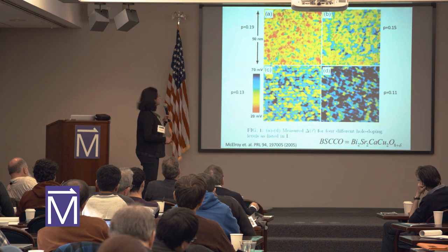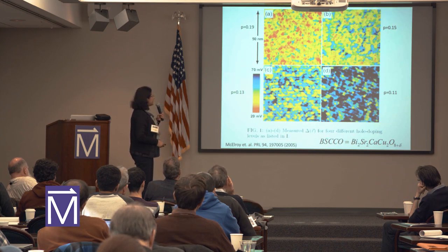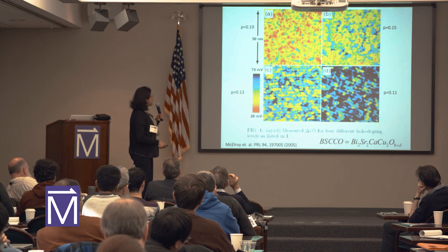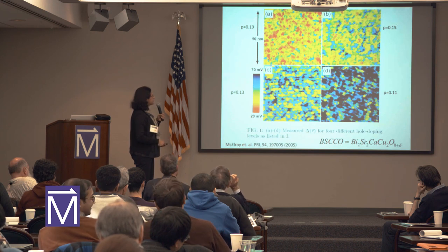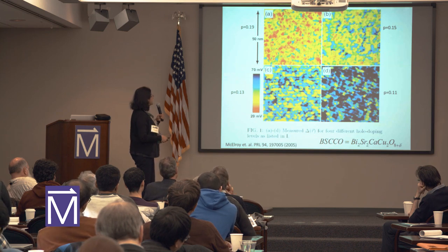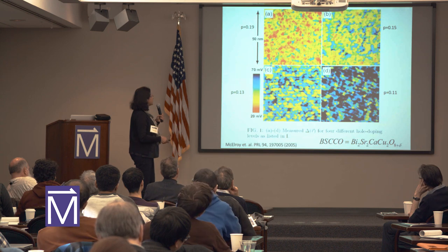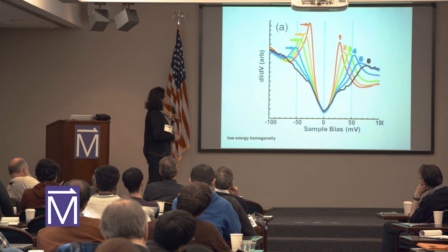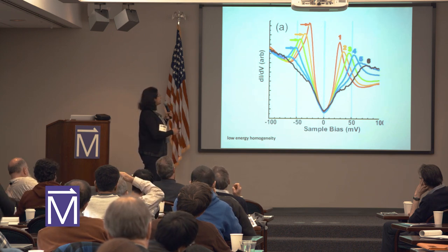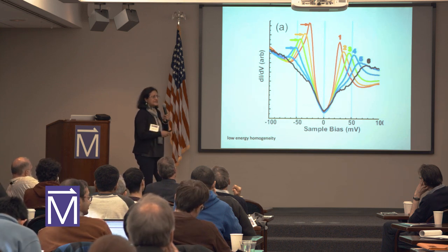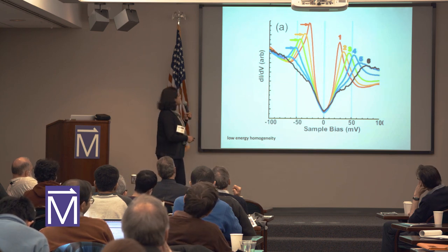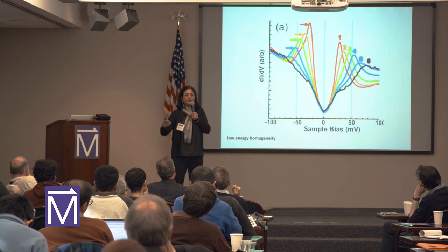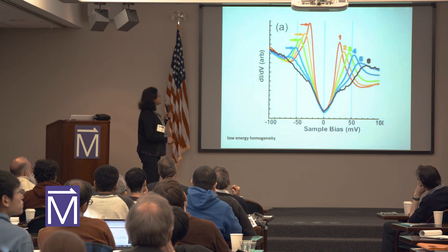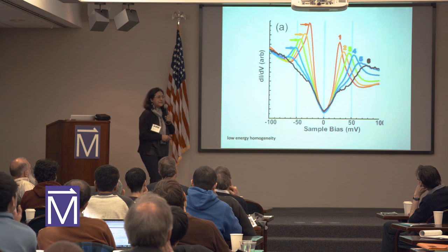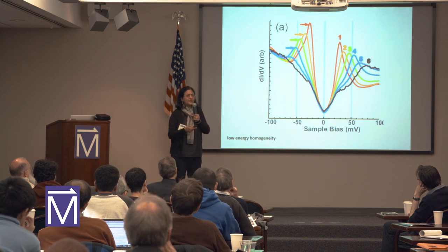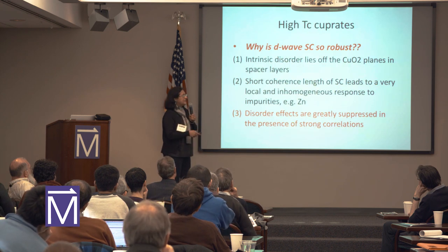Okay, so let me just quickly tell you about what was the D-wave story. So this is data from Seamus Davis's group, very old data now, where they look at scanning tunneling spectroscopy on BSCCO with oxygen doping, and they get these different colored pictures. They basically tell you regions of high conductance and low conductance. And when you plot them out, they show one remarkable feature that stands out, whereas the behavior at the coherence peaks is very different depending on whether you're at a high conductance region that has a sharp coherence peak or a low conductance region that is more broad. But what stands out is the low energy V in the density of states is extremely robust. And the question is, why is it so robust across very large changes in doping?